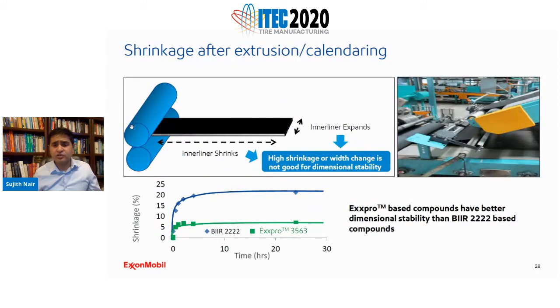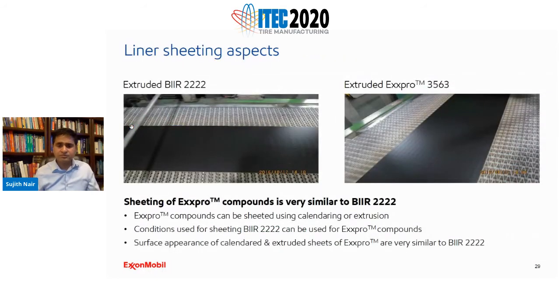I talked a little bit about the shrinkage. Bromobutyl tends to shrink in the machine direction and expand in the width direction. And this is not desirable because this shows that the material does not have good dimensional stability. In case of bromobutyl, the shrinkage is around 20-25%. In case of Exxpro, the shrinkage is around 7%. So it is much more dimensionally stable than bromobutyl.